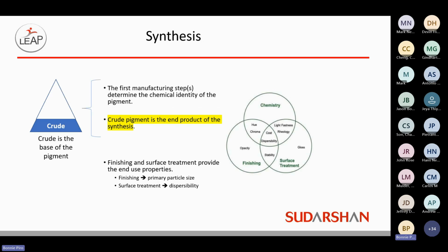So as far as the synthesis is concerned, we talked about this many times. About 75% of the performance really comes from the chemistry itself. And the remaining performance is then shifted by either the chemical finishing, which is typically a surface treatment or some other additive in the process, or mechanical with respect to what type of drying process is used, or a pulverization particle size reduction process. Each of those will shift the end performance for that particular CI.